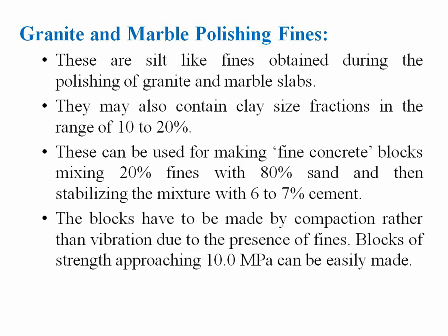The blocks have to be made by compaction rather than vibration, due to the presence of fine particles. Blocks of strength approaching 10 Newton per mm square can be easily made, that is, 10 MPa.